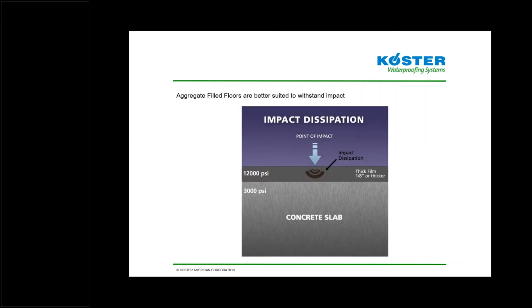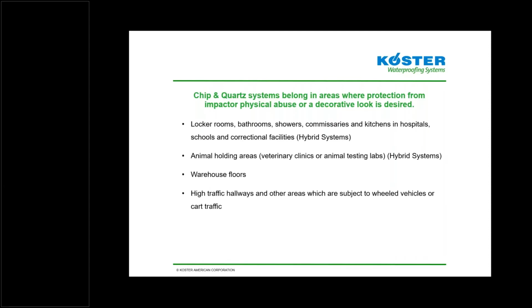Again, we talked about the difference where we saw impact resistance in terms of the thin film coatings and the thicker film aggregate filled systems. When we build these aggregate filled systems at 1/8 of an inch or higher, that epoxy is normally between 12 and 15,000 psi with these aggregate pieces. It does a much better job of dissipating the impact of any kind of direct point load and preventing the concrete from shattering or breaking. If we thought about maybe a 5 mil thin film system like in a hangar, that would not do very well to displace that load, and we may have issues with spalling or cracking in the concrete.